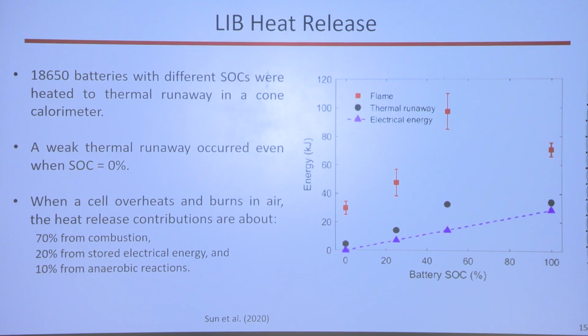But all the other lines really have huge uncertainties and need to do hundreds of burns, I think evidently more than they were able to do to get good statistics. So there's the thermal runaway energy, which seems to increase with the state of charge, and then the flame energy that also seems to increase with the state of charge. But it's not too clear from this plot, but in other sources what I found as the last bullet is when a cell like this overheats and burns in air, the heat release rate contributions are about 70% from combustion, so burning those electrolyte oils in the air, 20% from the stored energy, and about 10% from anaerobic reactions inside the battery.